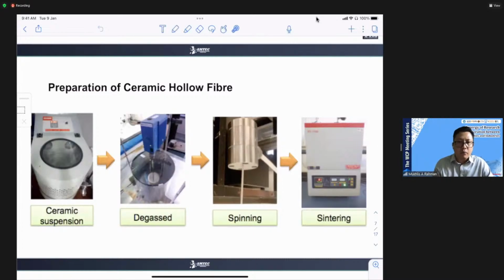After up to 4 to 5 days, we get a uniform suspension, but we can't use it directly to make the membrane. We need to degas it first, because during the milling process a lot of bubbles form. Even though it is just a bubble, it can cause defects in our membrane, and in our palladium membrane. We experienced this: only one bubble can burst our palladium membrane. That's no good, so we need to remove all of them before the spinning process.